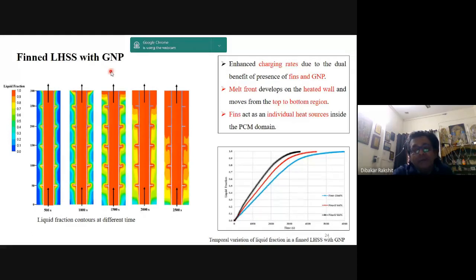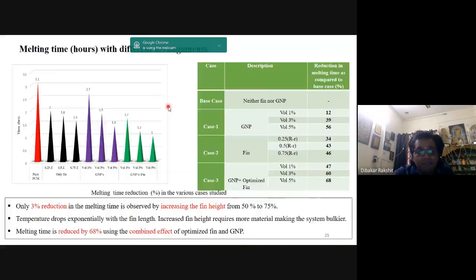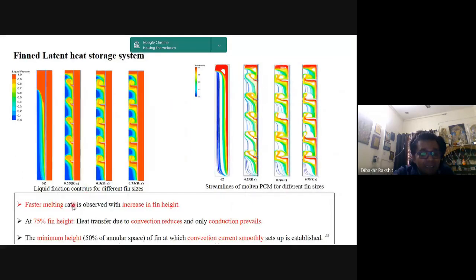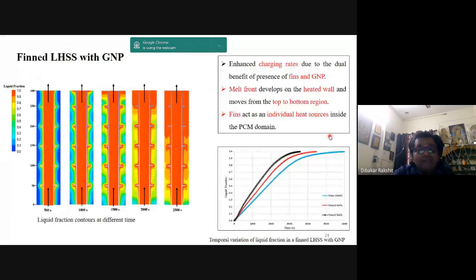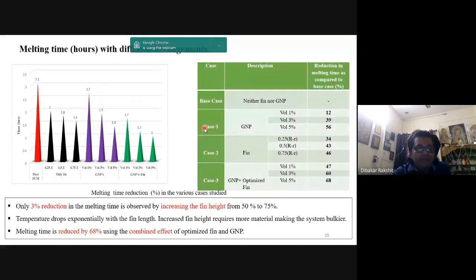And then one more observation we found was that these fins, which we utilize as the heat transfer enhancer, beyond a certain height actually act as individual heat sources inside the PCM. Like it acts as a thermal bridge, which is not a very good situation. So we wanted to avoid the situation where these fins were acting as heat sources inside the PCM.